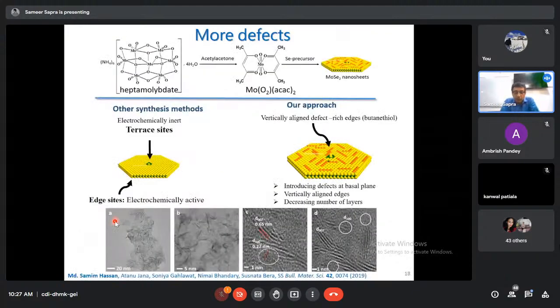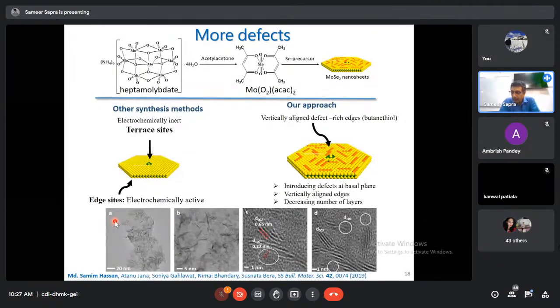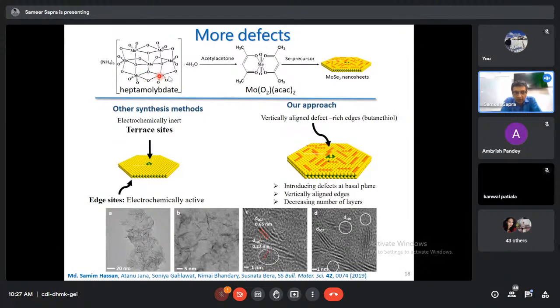So what you do if you wish to make molybdenum selenide is to take, about 4 or 5 years back, this heptamolybdate, make the acetylacetonate. Today you can get this off the shelf. So you can just take molybdenum acetylacetonate, heat it to a high temperature of 250 degrees, put some selenium precursor, which is selenium in oleylamine, and inject it at high temperature, and you get molybdenum selenide nanosheets. All right.